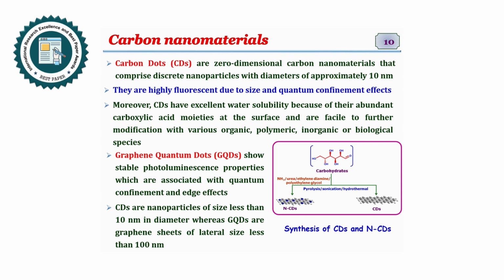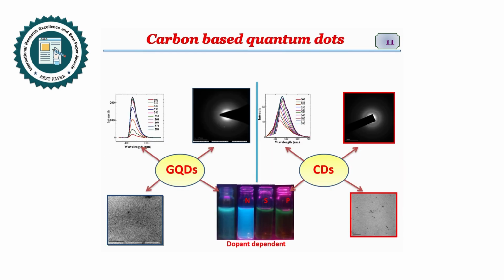Carbon dots are another kind of material. They are zero-dimensional carbon material comprising discrete nanoparticles with diameters of approximately 10 nanometers. GQDs are another material. They are in the size of 100 nanometers. This is the major difference between carbon dots and graphene quantum dots. GQDs exhibit stable photoluminescence, which is associated with quantum confinement and edge effects. Similarly, CDs also exhibit high fluorescence due to size and quantum confinement.